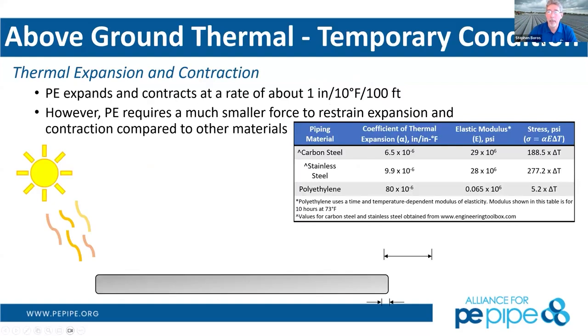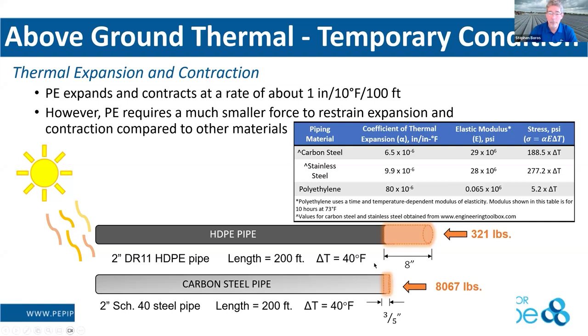Thermal expansion contraction. Polyethylene does have a higher thermal expansion coefficient. However, it's very easy to restrain because the force that it develops is very, very small. So with polyethylene pipe, let's say you've got a piece of 200 feet of pipe and a delta T of 40 degrees Fahrenheit, you may get, theoretically, as much as 8 inches of expansion from that. Well, to restrain that, it's only going to take 320 pounds. Whereas if you had carbon steel pipe, yeah, it may only move 3/4 of an inch, but it's going to take 8,000 pounds to restrain that piece of carbon steel pipe if you don't want it to move off that flange adapter or that valve that you may have in place. So again, you need to take all that into account with polyethylene.